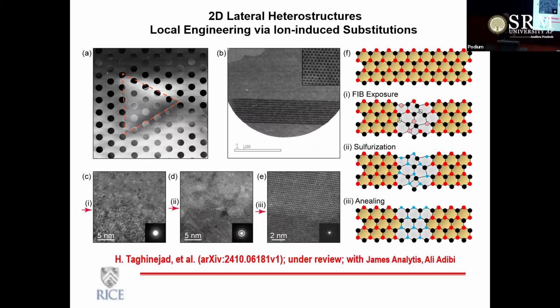And I'll show you one example, which is mostly done in Berkeley, but we were collaborators, that suggests the scalability of this approach, right? So most of the structures that you saw, these laterally distributed domains, were done by vapor phase techniques. But you could also create these layers and then locally go and change the layer in specific locations. So in this particular case, we actually grew these layers, let's say tungsten selenide or something like that, and then using electron beam or focused ion beam, go locally and create defects in these systems. And once you have defects, you can actually introduce another element and change the composition locally in those places. So for example, if I take tungsten selenide, I can remove some selenium from locations, and I can reintroduce sulfur in those locations.